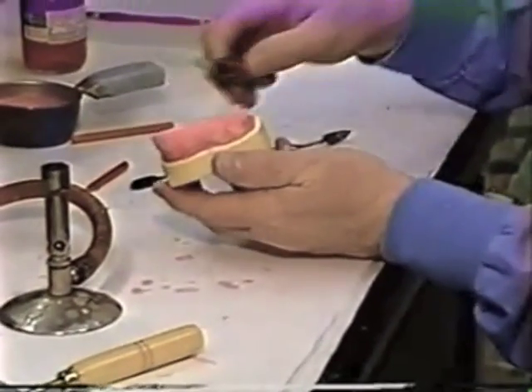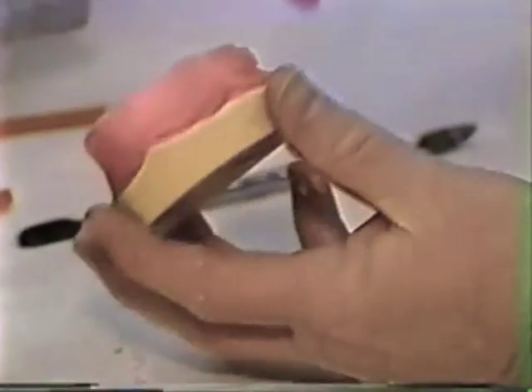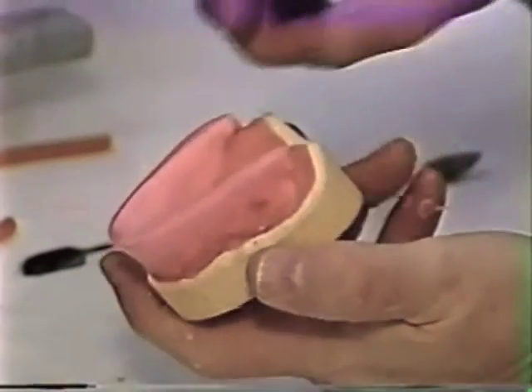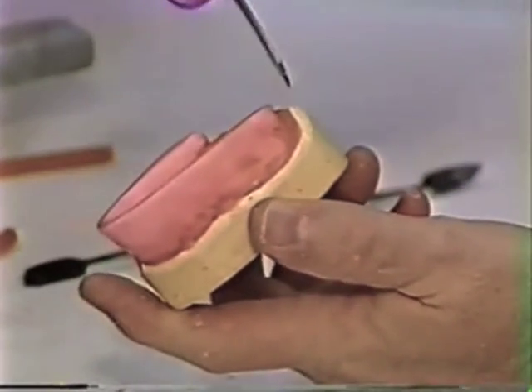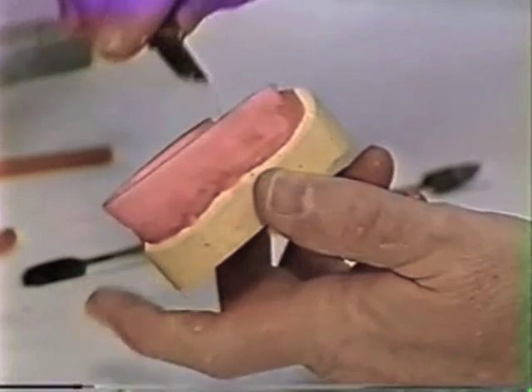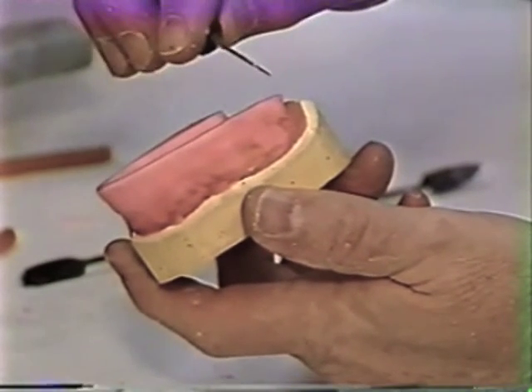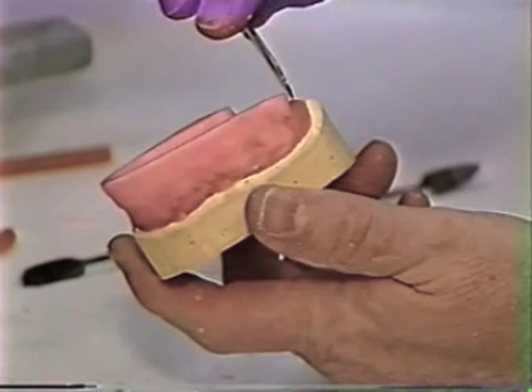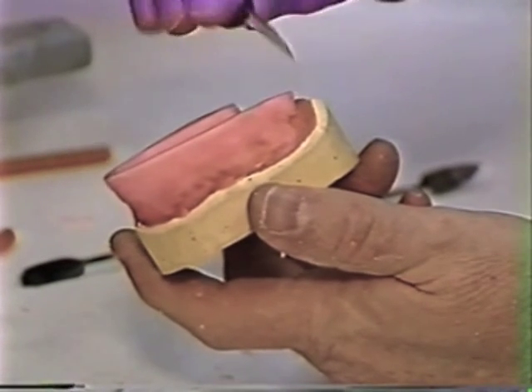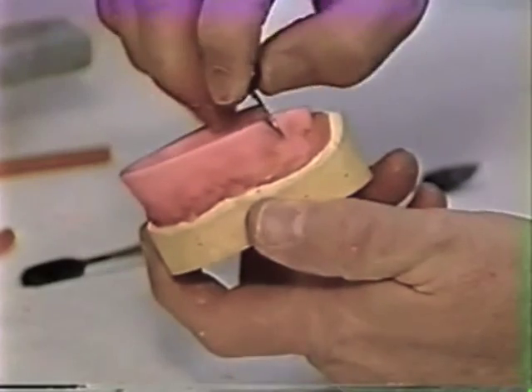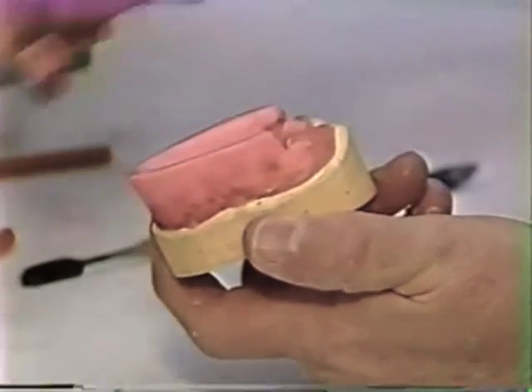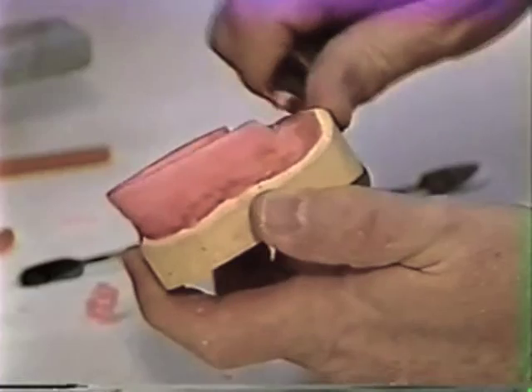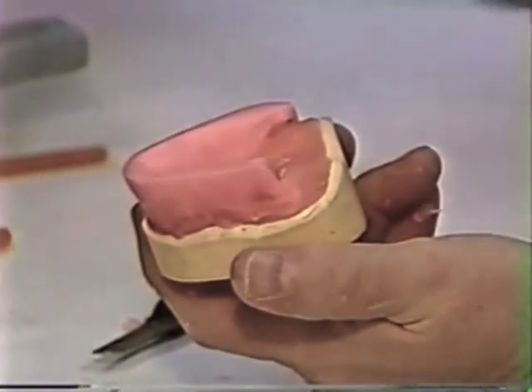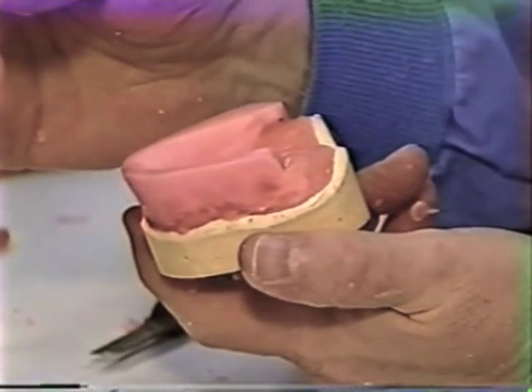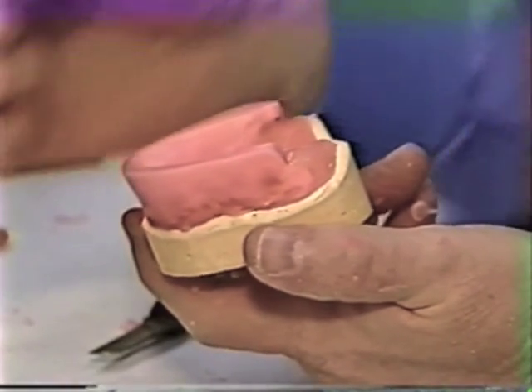At this point, we have a nice flat plane on the occlusal surface and incisal edges. It's relatively smooth at this point, but it's a little too long posteriorly. We like to cut this wax off and end this occlusion rim at about 1 centimeter anterior to the hamular notch. And the hamular notch is here, so we want to cut off about 1 centimeter of that at just about that level. And then we can take a spatula and smooth that out where we've made the cut.